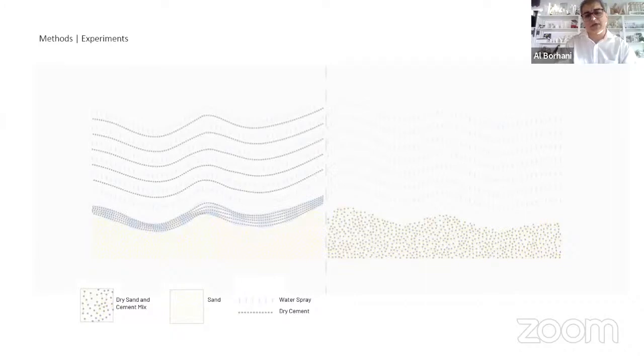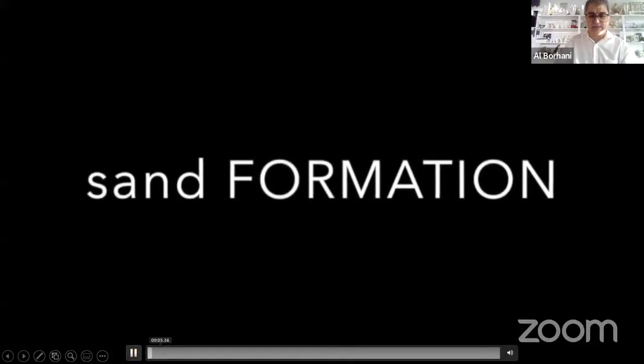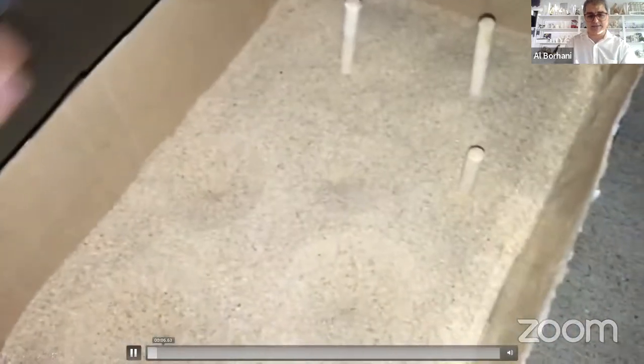But here we decided to use sand as a kind of pure material, and not contaminate it with cement, as long as we wanted to use it many times. As long as we decided to keep the sand pure, we add water and we add some layers of cement. Here probably we can see the process.